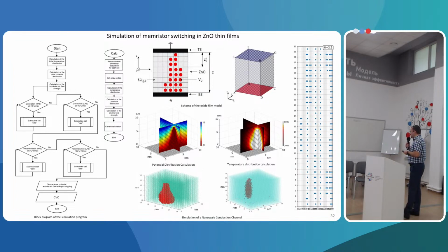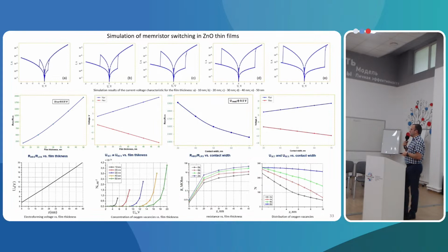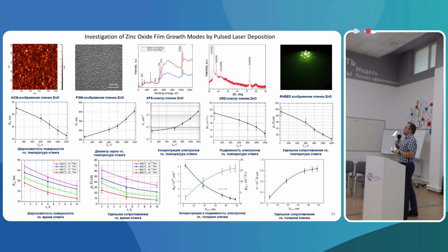For investigation of resistive switching in thin oxide films, we develop a simulation model based on Python programming, which provides us investigation of the influence of thickness on current voltage characteristics and on the ratio, on common parameters of switching like voltages, currents, resistance.